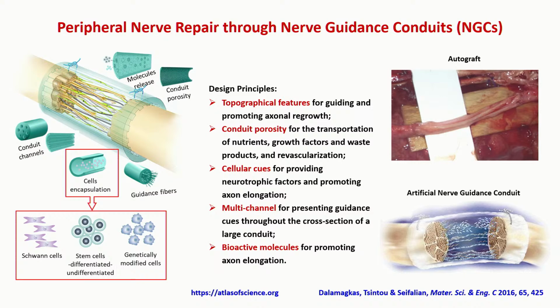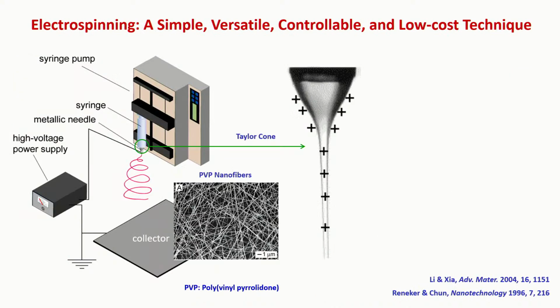And also you want this to be multiple channels instead of just a single channel. This is particularly important when you deal with thick nerves. When you treat thick nerves, if this lumen is too big, actually, eventually the impact from the surface will be lost, so you won't have any guidance at all. So in that case, this nerve will become tapered when they grow into the middle point of this conduit. So all of these are just basically some general ideas we have to follow when we design these conduits. And specifically, we are using electrospinning to fabricate the scaffolding materials.